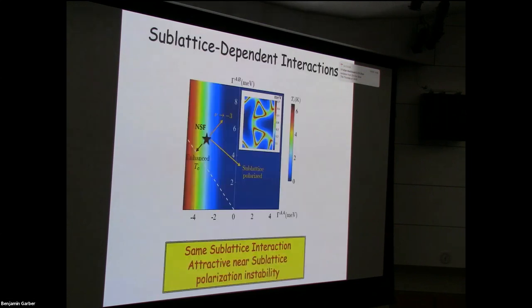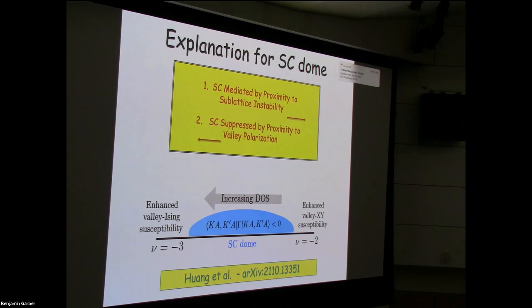You know, without going through the details, there is reason to think that the superconductivity in twisted bilayer graphene always pairs electrons from opposite valleys, because within the same valley, you break time reversal, the energy of K is actually not exactly the same as the energy of minus K. So if you assume that you always pair electrons in opposite valleys, valley singlet interactions, then being close to a valley polarization instability, which is common at, we're thought to be close to those instabilities at every odd filling factor, that's bad for superconductivity.